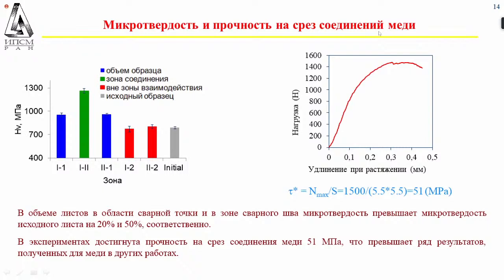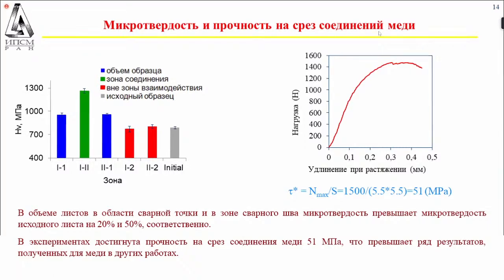And dividing the maximum efforts at which the destruction of this joint happens, we have counted 51 megapascals. At first, you may think that it's not really high, but in fact it's higher than the standard figures tested before.